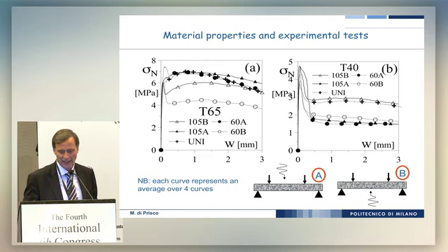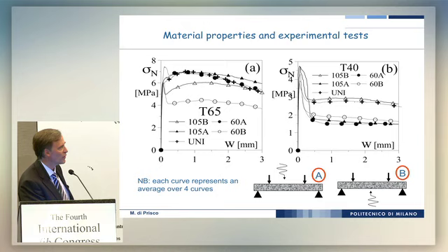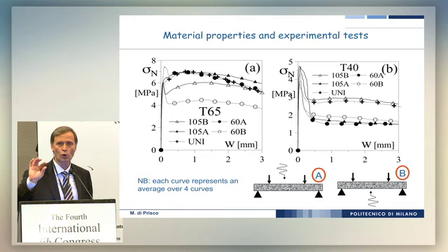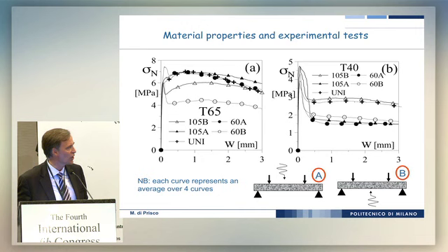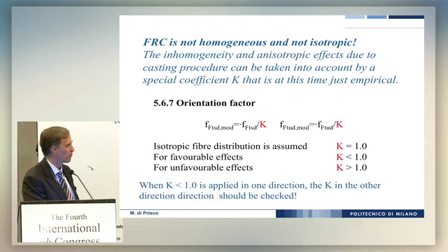Here we did the same for the other material, and you can also have a very strange situation if you don't analyze carefully. So the recommendation is when you have a thin-walled element, please consider also the unnotched specimen and try to analyze the real flexure behavior according to this approach.